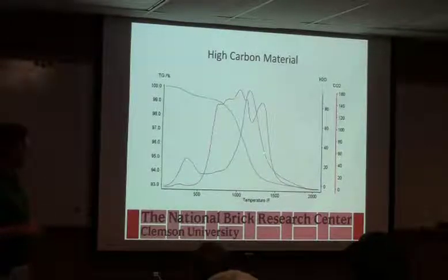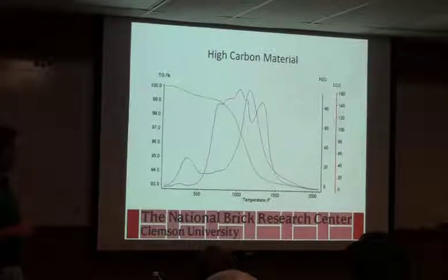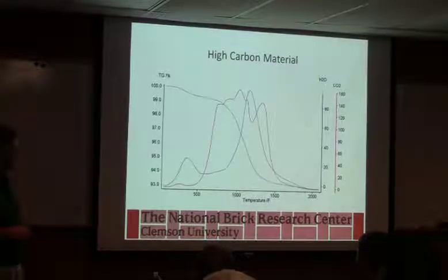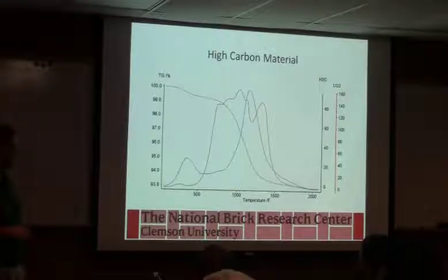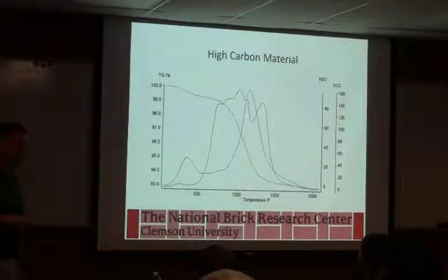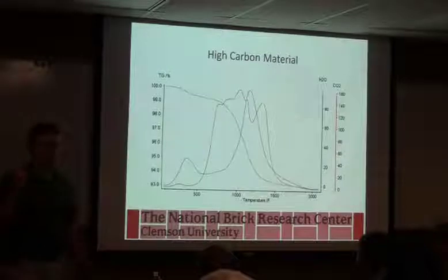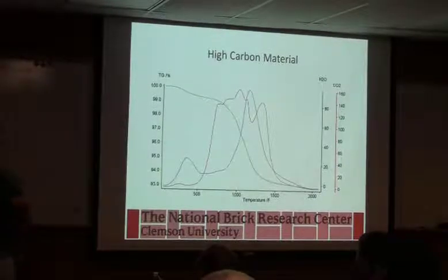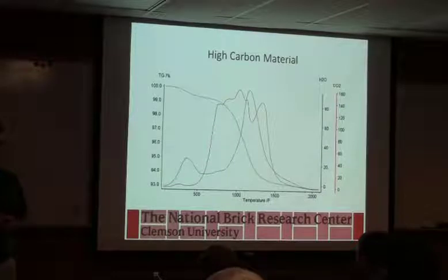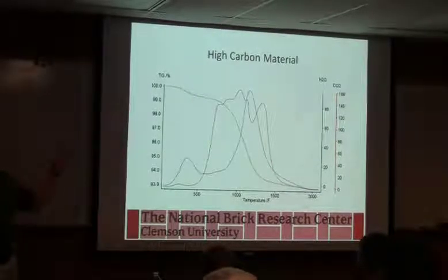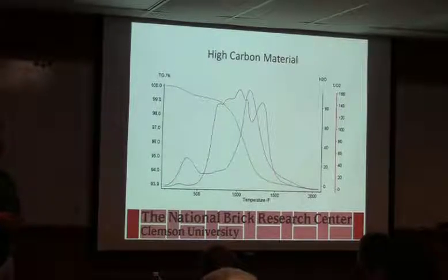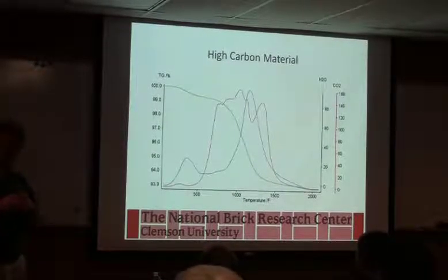So this is giving some ideas of, again, looking at the thermal gravimetric of seeing the peaks that you'd form from all the organics as they tried to burn off at all the different temperatures. And where this can play a major factor is if, depending on your firing schedule, you seal over the outside too quickly, you don't have time for all of that to get out of there, and when you heat up gas, what does it do? If it doesn't have a way to get out of the balloon, what does your brick do?